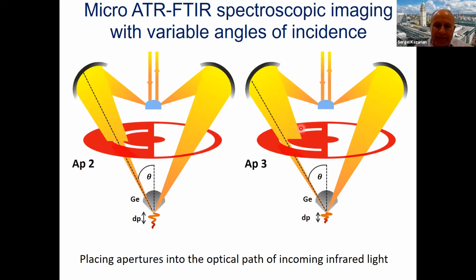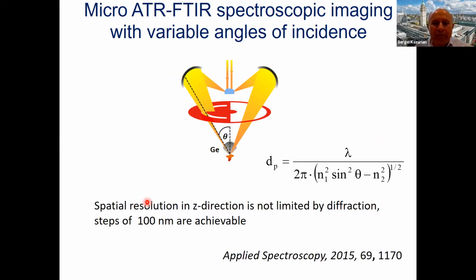And if the angle of incidence changes, you can select small angles, as you have seen on previous slides, or large angles, and the depth of penetration would be varied. So for example, photodegradation samples from the previous presentation might benefit from such an approach, because the angle of incidence is present in the depth of penetration equation. And so we were able to measure layers of different thickness by changing the angle of incidence,